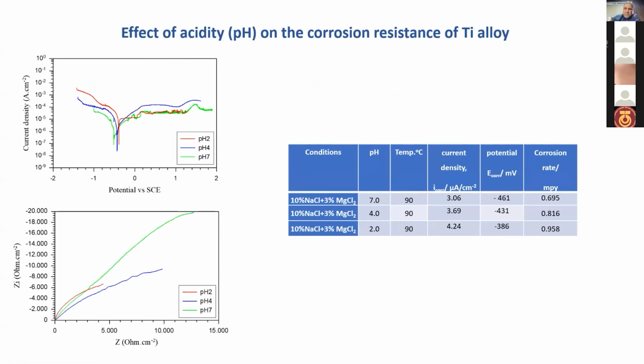The same also applies for the titanium alloys. We show that there is also a significant increase in the corrosion current density from about 3.06 to 4.24 microampere per centimeter square. And the corrosion rate also increased from 0.69 to 0.95 millimeter per year. Also, the electrochemical impedance spectroscopy indicates the same results, where the impedance decreased from about 23 kilo ohm for the sample tested at pH 7, to about 8 kilo ohm for the sample tested at pH 2.